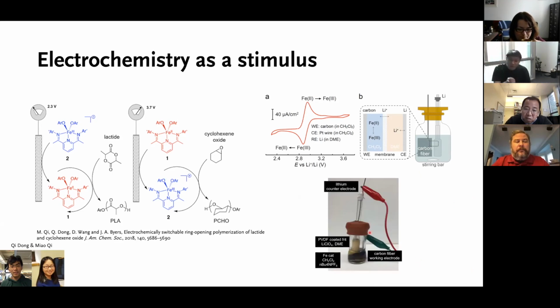And some other thoughts. This is how it looks in real life. I always consider it an ugly design, right? But it works great. One other challenge they had to overcome was the incompatibility of lithium with the solvent used for the polymerization, so they really used a different system for this. When you do a CV scan like this, the number of charges passing through the system is minimal. You really don't have to worry too much about the counter electrode design. But when you're doing electrolysis, when you're dealing with a large quantity of chemicals, this is something you need to care about. In other words, for chemical synthesis, electrochemical synthesis, this is particularly important.